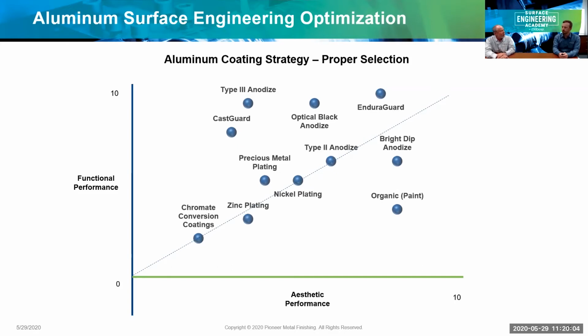We also have an anodizing process that we call optical black. The optical black is a functional coating in that standard anodizing is done with organic colorants. This is an inorganic colorant that when it's exposed to high intensity light, even laser type lighting, it doesn't break the color down. So from a functional reason, that's critical. We have our EnduraGuard coating, which was primarily designed for castings. With that process, we've been able to provide an anodizing, again, that doesn't have the creep corrosion that can hold up to thousands of hours of salt spray. It's been approved for marine applications in salt water. We've also got the standard type 2 anodizing.